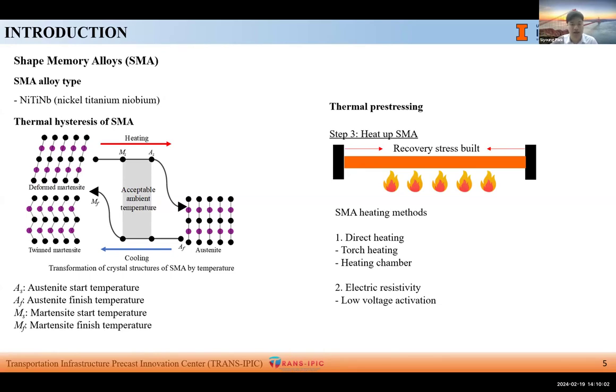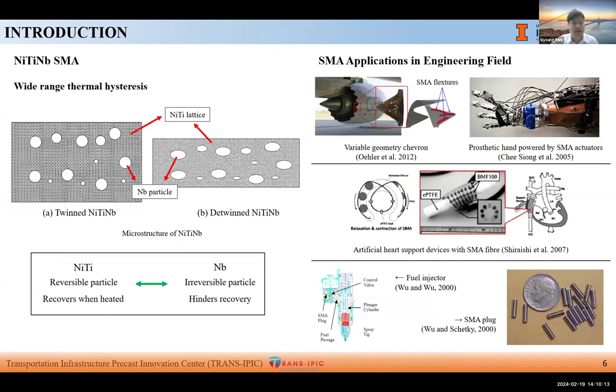Usually, direct heating is done by torch heating or placing in a heating chamber, and electric activation is done by applying low voltage activation. Among diverse SMA types, nickel titanium niobium SMA was selected for the analysis. Nickel titanium niobium is composed of reversible nickel titanium particles and irreversible niobium.